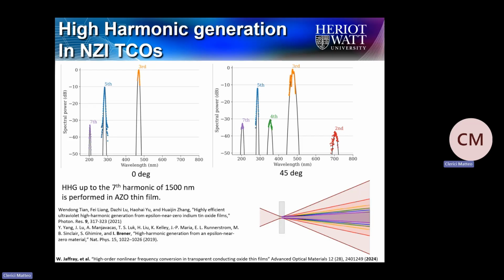And because of that, now you have a system, because you are playing with the electron free gas, that is like playing with the plasma, and so it is intuitive that you can have very interesting effects in high harmonic generation. This is one example of a set of results that we published just at the end of 2024. And it's interesting to see how, given the very large nonlinearity, we can also, for angular incidence of our pulse, generate both odd and even harmonics.